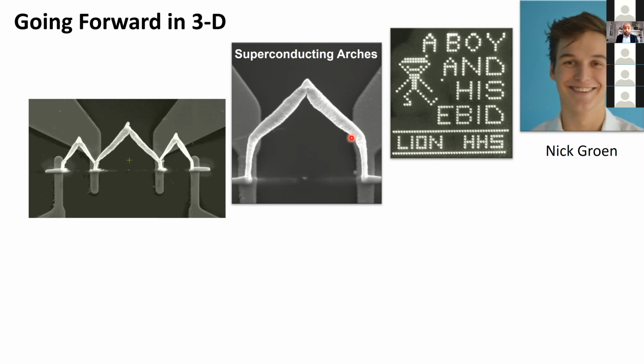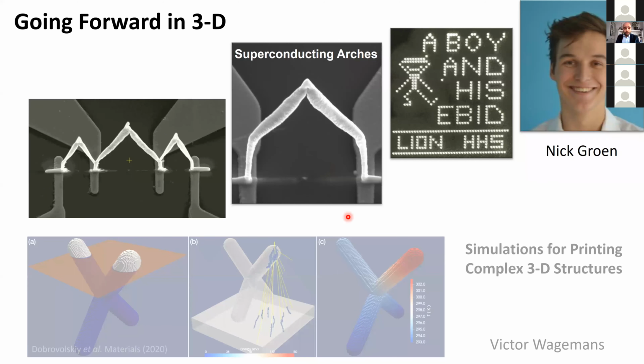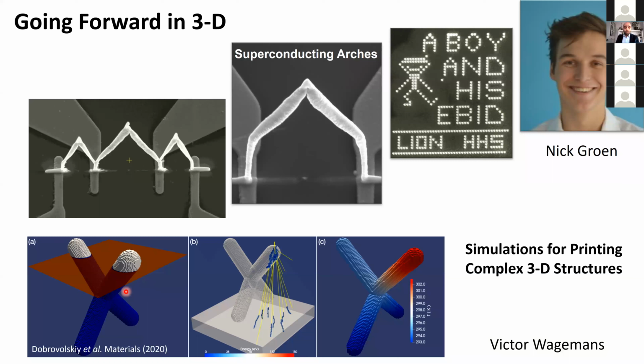And this would, of course, be very interesting because now we can actually make superconducting networks that are not limited to planar geometry, but can also go in all three dimensions. But to really get a handle on that, we are also now working on Monte Carlo finite element hybrid simulations. Because the picture I showed you at the beginning, which was just the molecule goes in and gets dissociated and forms a deposit, is a grossly simplified picture.